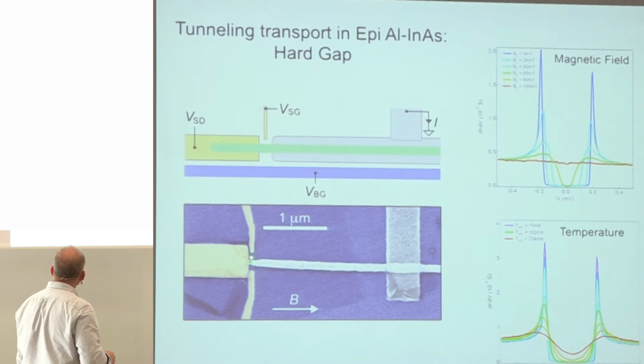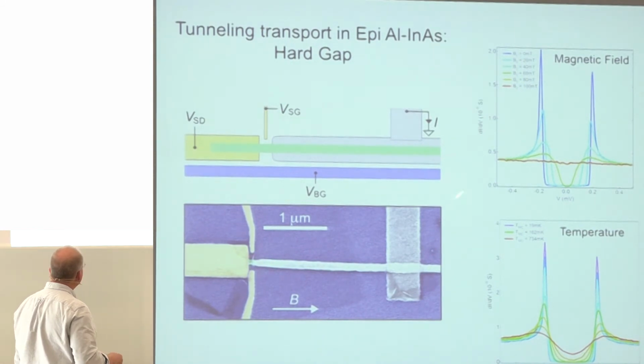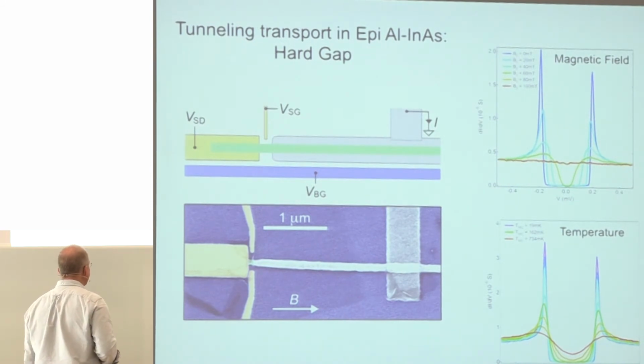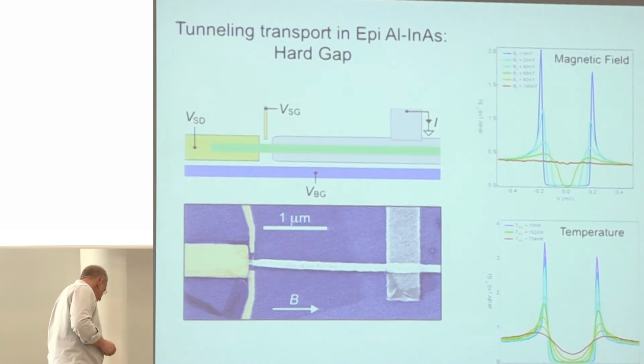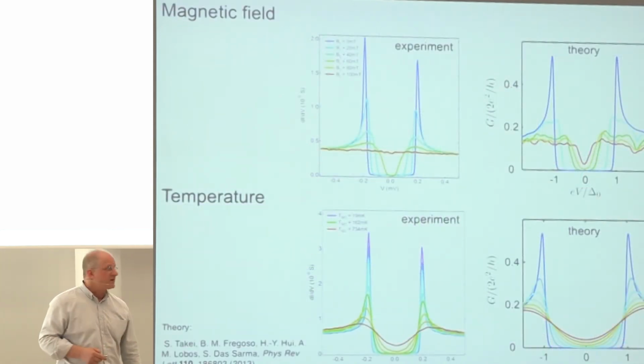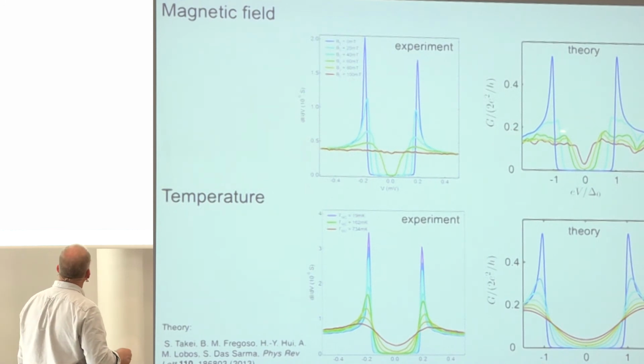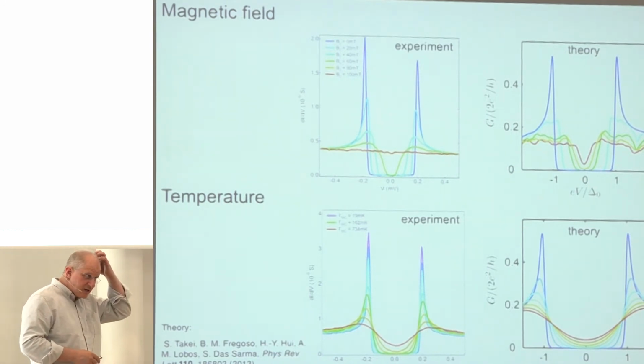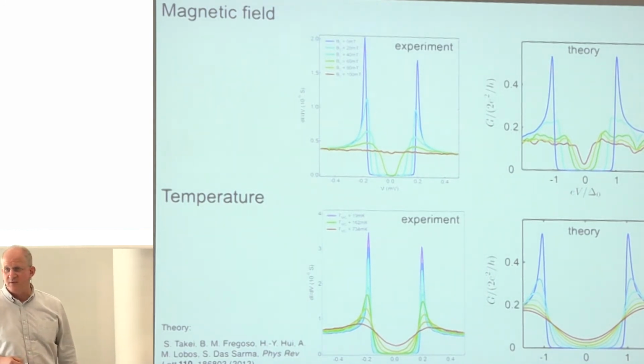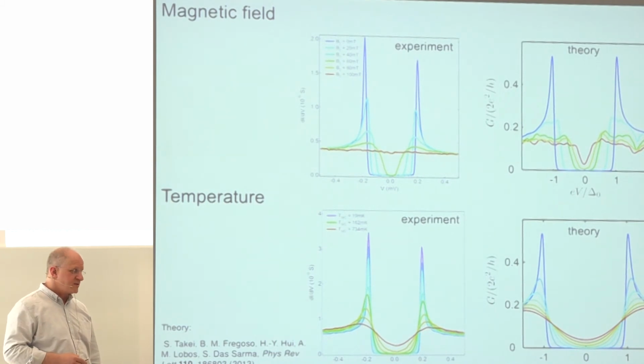If you make a tunnel barrier just like in the Delft geometry and you make a tunneling from this proximatized superconducting state into a gold lead, you'll find now the hard gap is restored, and as a function of magnetic field and temperature, the curves reproduce exactly what you would expect theoretically. Here is the theoretical curve for what happens as a function of magnetic field. Here's the theoretical curve for what would happen as a function of temperature, and you see that you're just getting exactly what you'd think you would get. So that theory paper about the soft gap appears to be correct. The quality of the interface seemed to make a lot of difference.